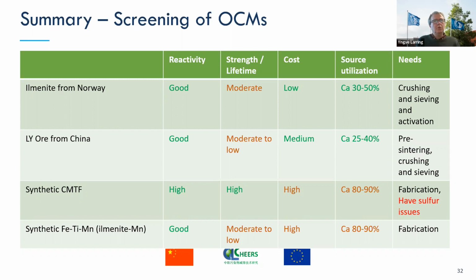But if you look at the total sieving of a whole system, you only utilize a small fraction of mineral from an ore, for example. Especially from the manganese ore, like ore from China, you will always have a lot more dust in the manganese ore because it's easier to crush, meaning that you get lower fraction, which you can use for a CLC system in the long run. If you compare this with synthetic materials, where you can produce the correct fraction directly, there is less time, fewer losses here.